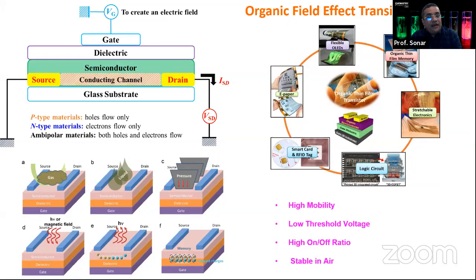Particularly looking at some of these new exciting materials like 2D materials, graphene is a wonder material. Why is graphene not that successful in electronic devices, particularly in transistors? Because the graphene material has a very small band gap, and due to that the on-off ratio suffers. When you apply the gate electrode voltage, the transistor is on, but when you stop applying the gate voltage, then the transistor is off. During the off state you should not get a leakage current, but in the case of graphene you get a huge amount of leakage current, and that's why the on-off ratio values are very lousy, close to 10 or something.